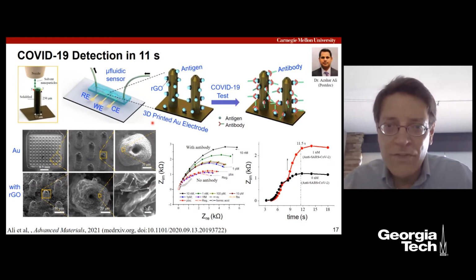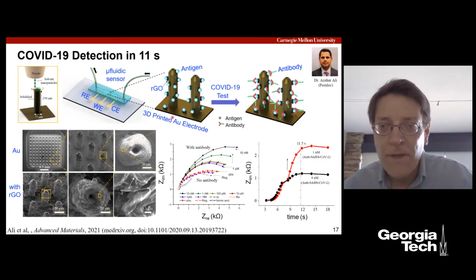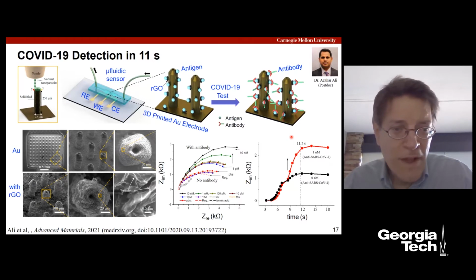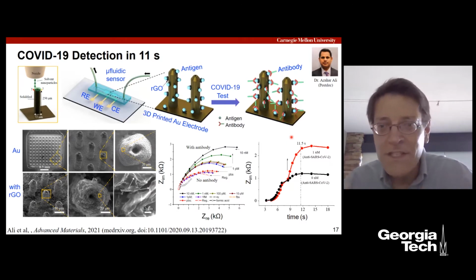And in fact, they tried 2 different antigens for 2 different COVID-19 antibodies, and found, as you see in the lower right here, with electrochemical impedance spectroscopy, where they sweep frequency between a working electrode and a reference electrode on their electrochemical miniature microfluidic setup, they're able to identify within 11 seconds that there's a SARS-CoV-2 antibody present. And so that we think is obviously pretty exciting, but what's also interesting about this is this system can get regenerated within on the order of a minute, with a flush of the system with formic acid to clean off the antibody, and then it's ready for reuse. So they're looking at how to take the next step.